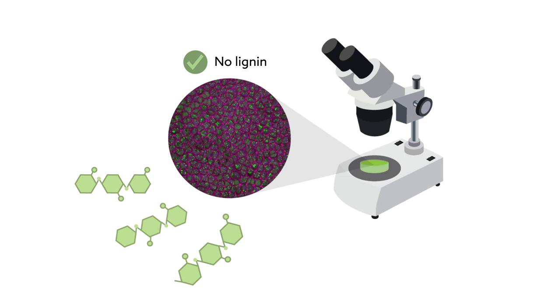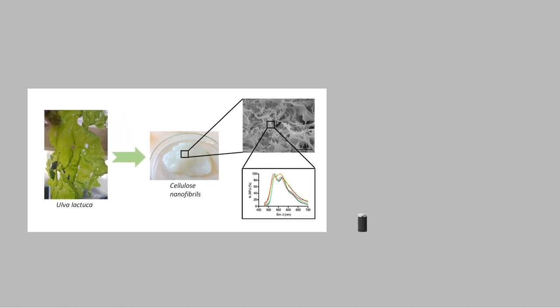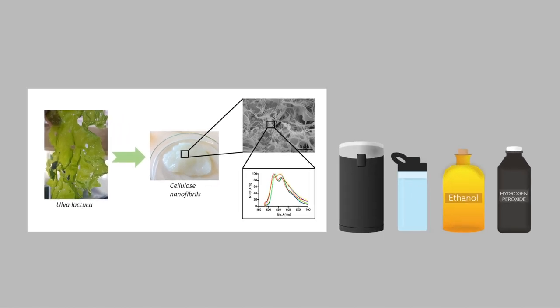Just how easy? Researchers from Sweden recently obtained highly pure cellulose and cellulose nanofibrils from freeze-dried bits of the algae using little more than a coffee grinder, water, ethanol, and minute amounts of hydrogen peroxide. Though simple, their method produced nanofibrils composed of up to 90% cellulose.